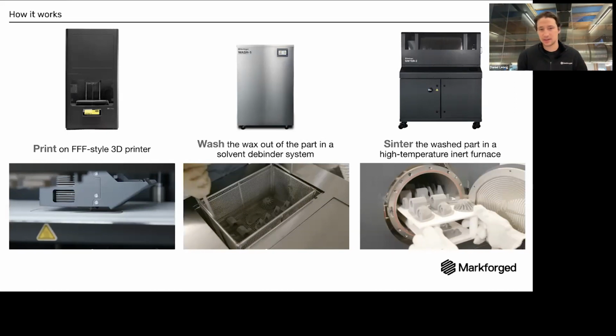So the second step is debind. Debind or wash, they mean the same thing. Essentially what we're doing is we're putting this part that we call a green part into a solvent bath. When you print it, it feels like clay. It's actually magnetic, but it doesn't look or feel like metal at all. The solvent bath dissolves the first of the two binders, and that takes a decent amount of time. It takes an exponential amount of time based on how thick the solid geometry is. The result is a part that we call a brown part. It functionally looks the same as a green part, but it has micro channels dissolved into it.